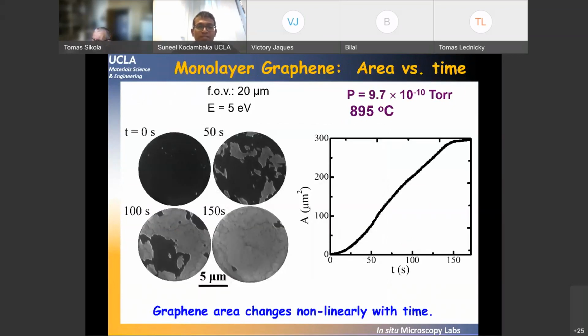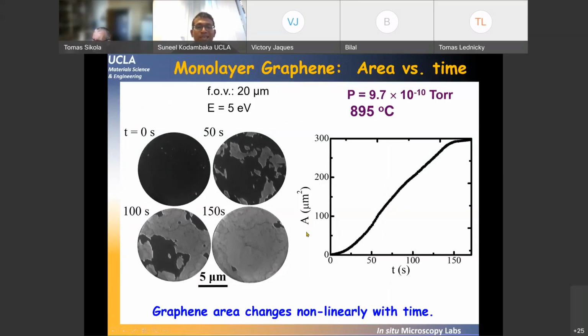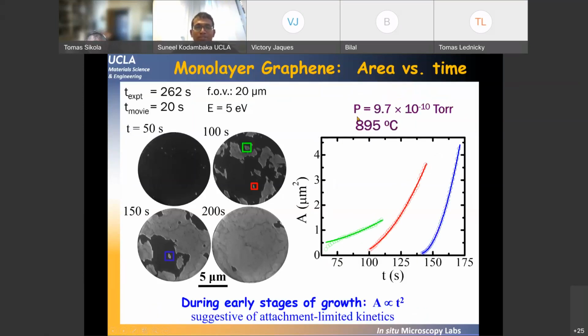We can use these images to quantify the area of the graphene domains as a function of annealing time. This is done in vacuum at about 895 degrees. And you see the total graphene coverage increases as a function of time. Initially there is only the palladium surface, and finally there's a monolayer graphene-covered surface. Okay, now we'll go into the details.